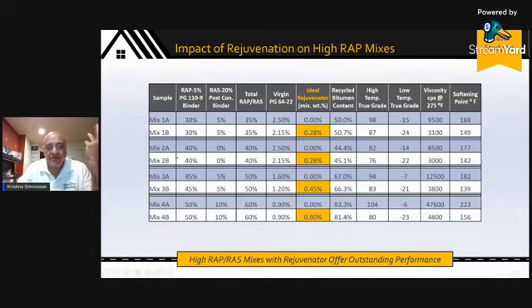Let's just pick mix 2A. Mix 2A contains 40% reclaimed asphalt pavement. So a mix that contains 40% of RAP with no rejuvenator, and these are the kinds of properties you get out of it. Mix 2B has the same 40%, same RAP, and in this case, we've added about 0.28% by weight of rejuvenator. Right away, you can see some important effects.